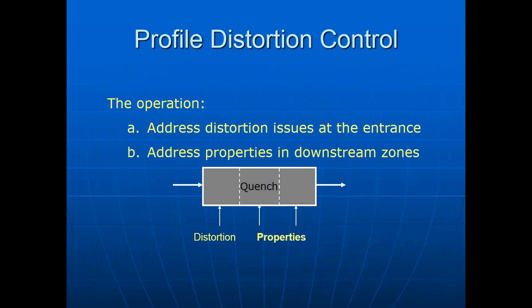By contrast, if you are struggling with a geometry issue, you only go to zone 1 of the quench and turn down the cooling rate there. You don't turn down the rest of the quench because, again, that's where you have the highest delta T, the highest cooling rate will occur as the profile enters the quench, and it is also where the metal is the softest because it's hottest.